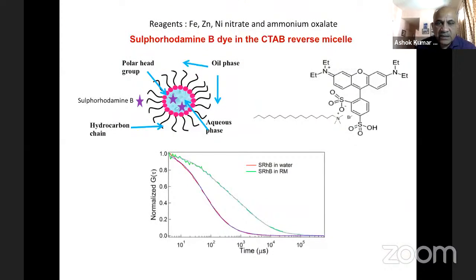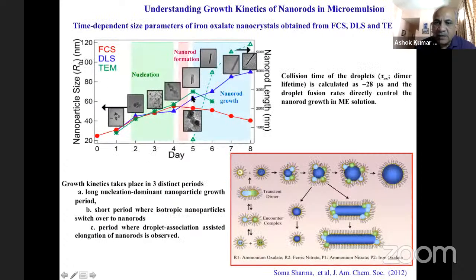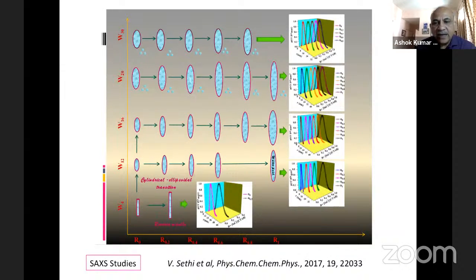So this is the interface of a droplet. And if you put some additional ions, they will go and interfere there, and the droplet structure will be modified. And that is what we do. We add an ion called salicylate ion, and as the concentration of that ion is changing, we can vary the shape. So you see these are more elongated, ellipsoidal, and at some W naught, they tend to become more round. And so with these two parameters playing, we can get several shapes.